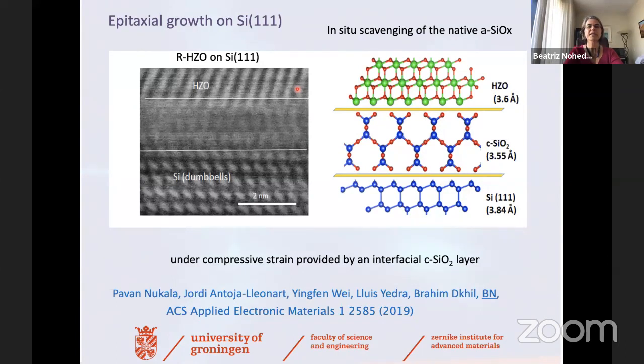So both on gallium nitride and silicon, and also on sapphire, one can use the template, the symmetry of the substrate, to grow this rhombohedral phase. And actually to achieve quite a nice control. In this way, you can do in situ scavenging of the native oxide layer that grows on top of the silicon.